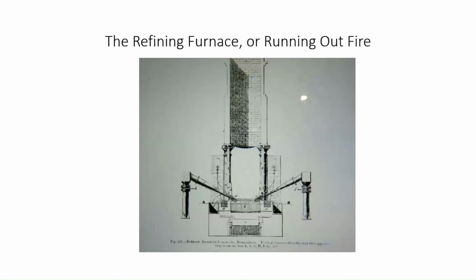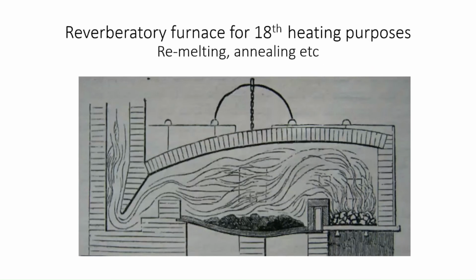They then took that iron and at red heat, it still had quite a high carbon content, still had other things in it, but they were able to bash it into a flat plate. But at that temperature, in doing so, they opened up some grains, opened up wherever the sulfur was able to be removed, washed it in lye to get rid of any sulfur that was so revealed. And then they put these bits of iron broken up into crucibles, put a lid on, and they put them in a reverberatory furnace. Now, a reverberatory furnace was the general heating process that was used throughout the 18th century.